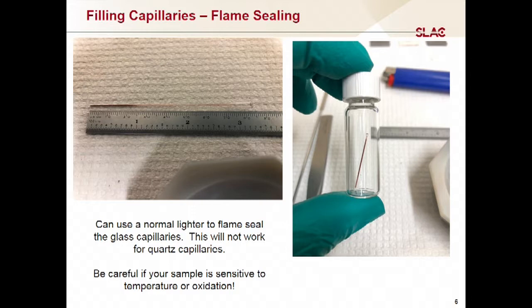So a couple of notes. I flame sealed this one because it was glass. If I was using a quartz capillary, you can't do this. The flame will not be hot enough to melt the quartz. You need a much hotter torch. You can do it, but I would recommend, if you want to use quartz capillaries, flame sealing is probably not the way to go.